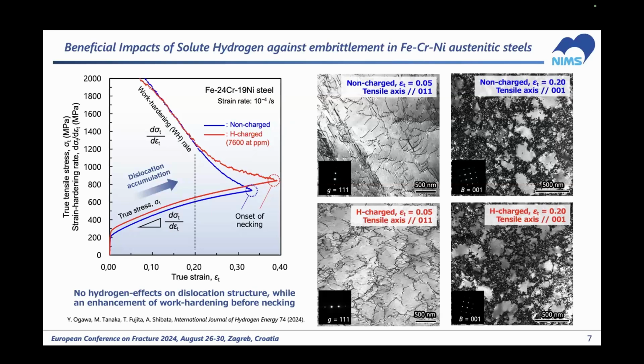And after the yielding, hydrogen parallelly shifted the stress-strain curve upward without any significant effect on the work hardening characteristics. So this was at least until the strain reached almost 20%. Under this strain regime, the dislocations initially exhibited planar arrangement and then transitioned into cell structures, but no hydrogen effect was found on the internal dislocation structures. But after that, as you can see here, the hydrogen caused a great increase in the work hardening rate prior to the necking. So the uniform elongation was increased by solute hydrogen.